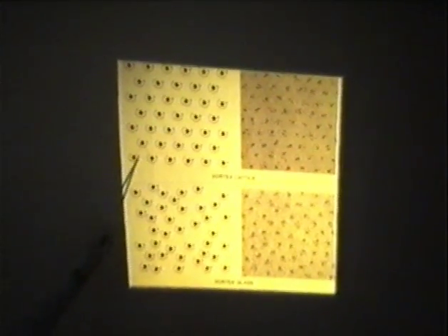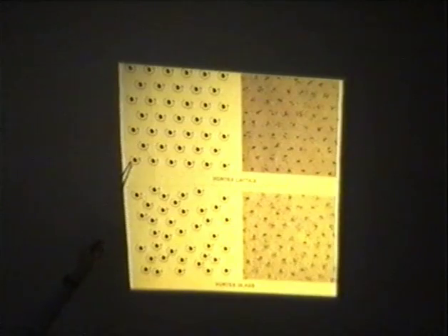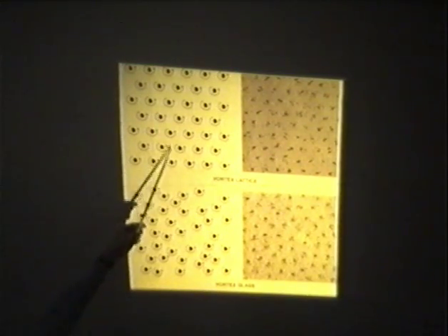So you imagine you're looking down the direction of the magnetic field that's been applied to a superconductor, and here the vortices have begun to allow the magnetic field to penetrate into the superconductor, but surrounding them is still superconducting material, so the resistance is still zero, because the zero resistance material shorts out the normal material in the vortices.